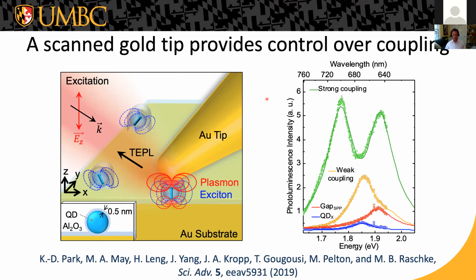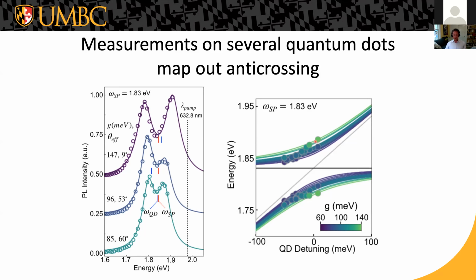The tip is always the same, but the quantum dots are all slightly different. They have slightly different size and shape, so they have slightly different transition energies. And we map out the detuning between the quantum dot and the tip and see a characteristic anti-crossing behavior that is a defining feature of these plasmon exciton polaritons. And there's some dispersion, some width to this anti-crossing behavior because the quantum dots also, in this case, have a random orientation, which means that their dipole moments are oriented in different directions compared to the polarization of this gap-plasmon mode, which is normal to the metal surface. So that misorientation between the two of them affects their coupling strength. But within that range, we still get the anti-crossing that we expect.